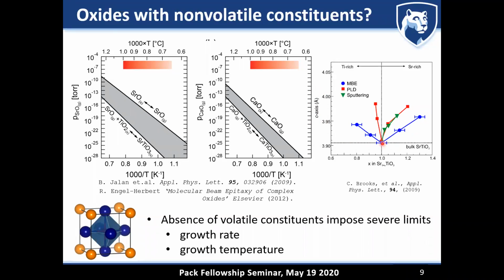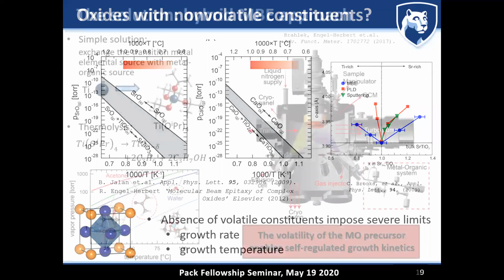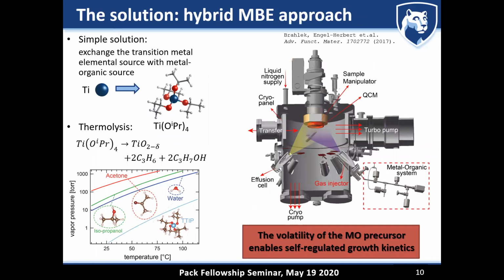And you can see that you typically only have one very specific flux composition in which you can achieve this. That means in all typical deposition techniques for the growth of calcium titanate or strontium titanate, this self-regulated growth window cannot be accessed. And that's really the ultimate challenge if you want to grow high quality complex oxide films. And the solution to this is something that we started working on over 10 years ago. And there's a review article that you can look at.